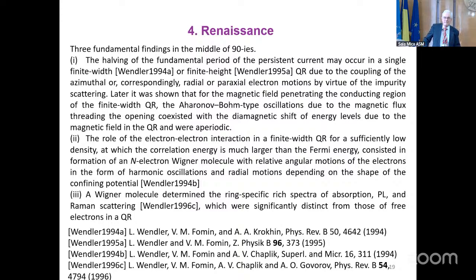The first is that the halving of the fundamental period may occur in a single finite width or finite height quantum ring due to the coupling of the azimuthal or radial electron motion by virtue of the impurity scattering. This was an experimental fact which was surprising, but it turned out that it can be tackled if you take into account the presence of impurities, which reduced the symmetry, but they did not reduce the topology. Therefore, there was persistent current, but not like in an ideal ring.